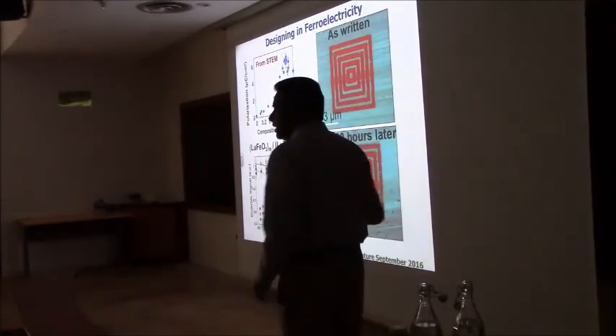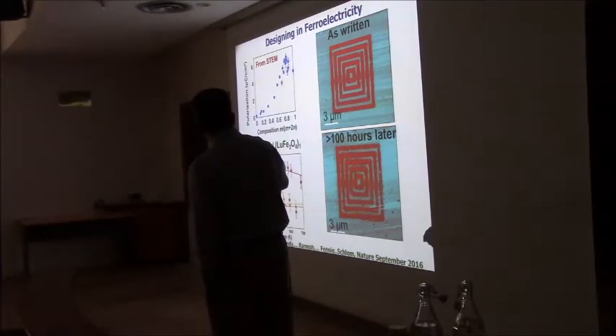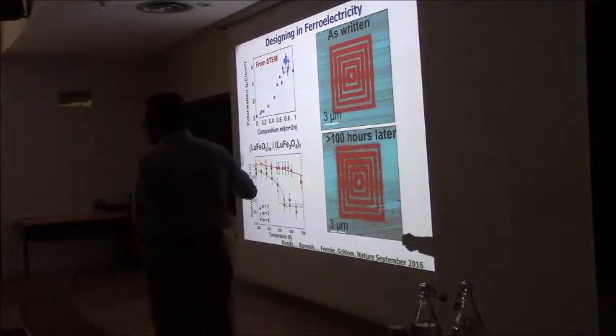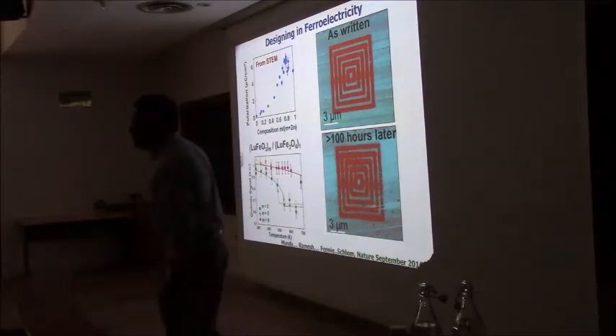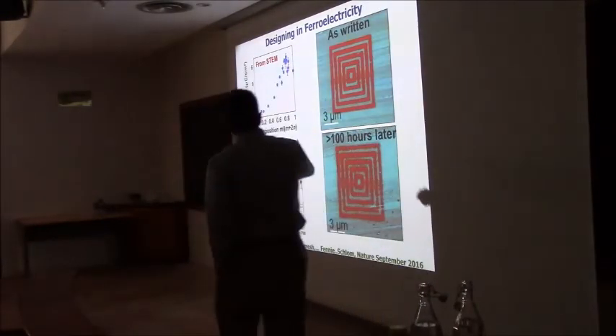There's a difference of the order of about 20-30%, very robust. And this is now for the 1 to 3. That difference is smaller. And again, it's telling you that indeed this one summarizes the dichroism data. It shows the phase transition from the ferroelectric state to something which is non-ferroelectric. M equals 9 goes all the way because the TC for that is almost the same as the 113 phase. Okay, all good. And the polarization from STEM is of the order of about 3 to 5 microcoulombs per centimeter squared.